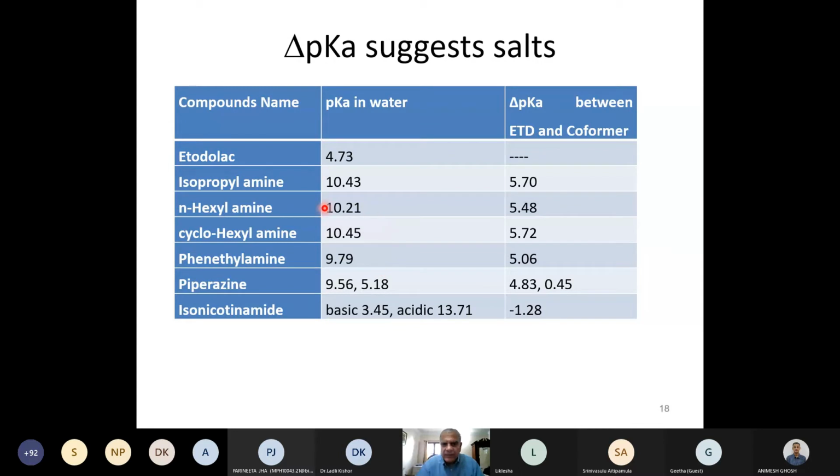And we looked at several amines, and the idea was to scan basically aliphatic, both cyclic and aliphatic amines, and see what kind of result we get, whether it's a salt or a co-crystal, and, B, the improvement in solubility and dissolution. And the third important thing you want to see is whether the salt or the co-crystal complex is stable to the conditions of the solubility and dissolution experiment, or whether it dissociates and decomposes.